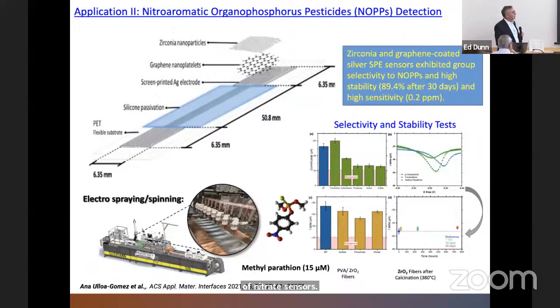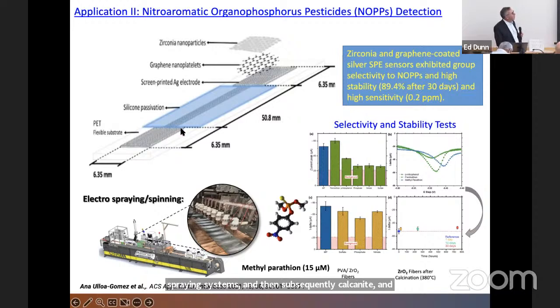This is another demonstration of one of our industrial presenters who is sitting in the front, Anna, a PhD thesis. And this happens to be essentially making pesticide sensors, and that's used on this Maxwell machine. It has many requirements, including screen printing the silver electrodes, graphene nanoplatelets, and the zirconia nanoparticles generated by these electrospraying systems, and then subsequently calcined, and then subsequently the silicone passivation layers put on top of it. And the whole system has turned out to be rather robust, with high stability and rather high sensitivity, 0.2 ppm, as you can see here.